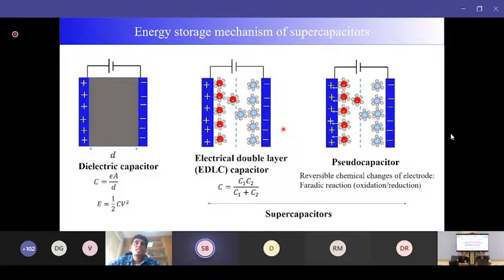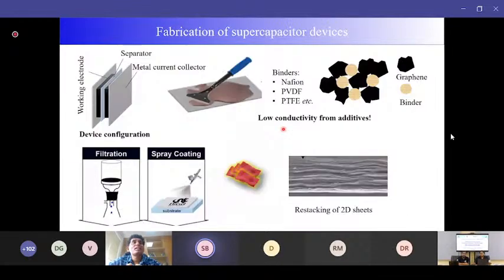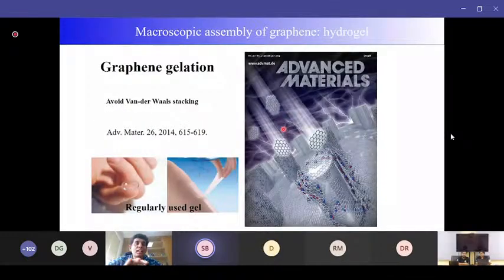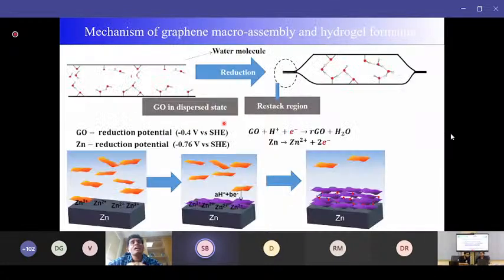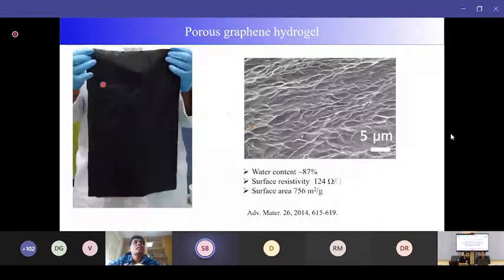Yeah, that's a good question actually. So definitely we can do it at higher current density. But if you do it at higher current density, you need to consider materials like graphene based materials. Graphene based materials are very stable. For EDLC material, definitely we can do the stability test at higher current. There is no issue. But if we use any pseudo capacitance and do the cyclic stability test, cyclic stability means we are charging and discharging. So we need to consider what is the stability of this material at a higher current density.